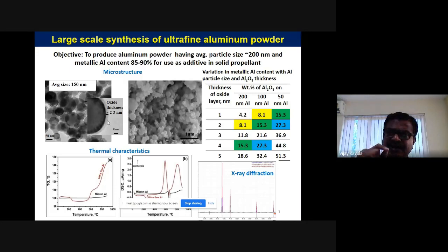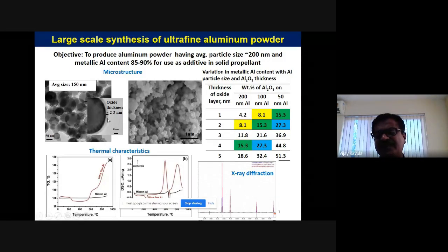But they should start burning even with a small spark. So that's why we have optimized a 2 to 3 nanometer oxide layer. You can see that typically 2 to 3 nanometers, a very, very fine oxide layer, is sufficient to improve the shelf life, to stop it from self-oxidizing, and at the same time burn it when you put a little spark.